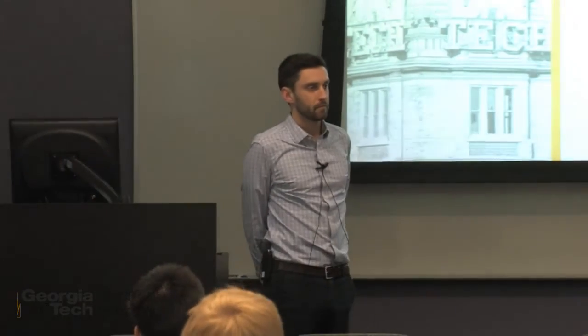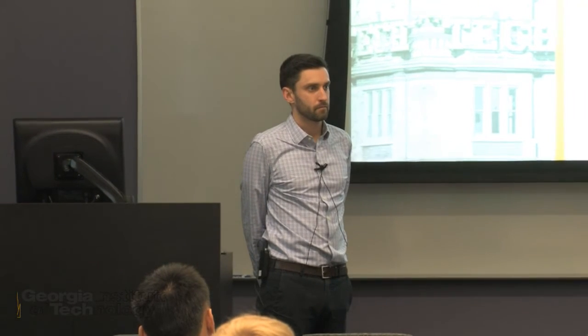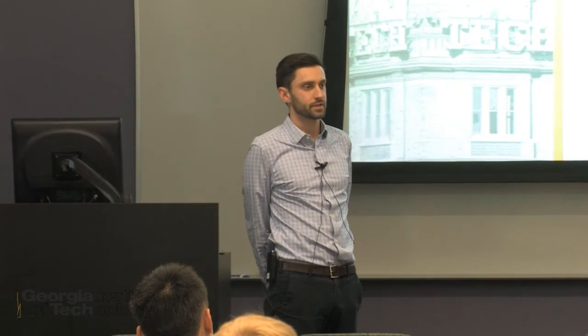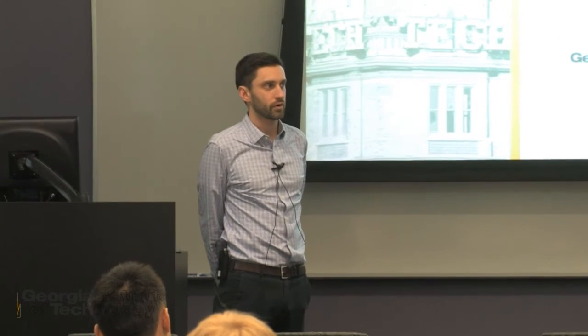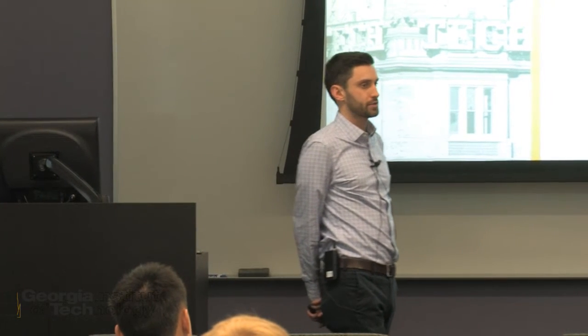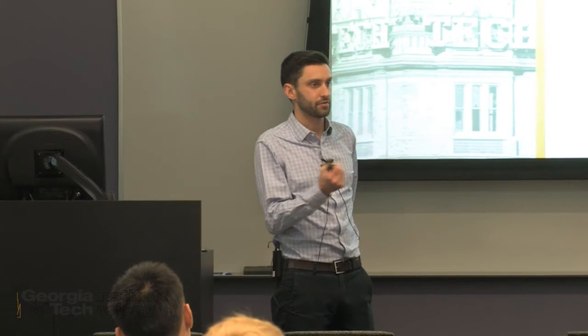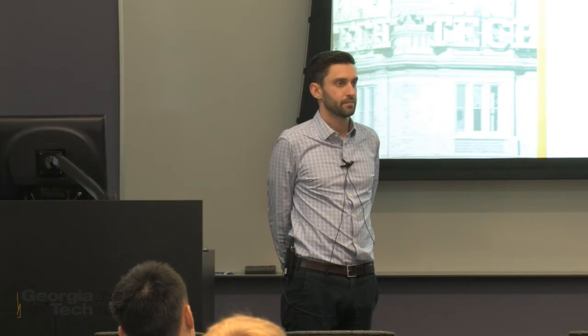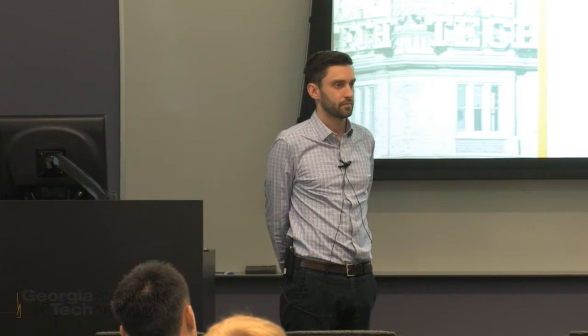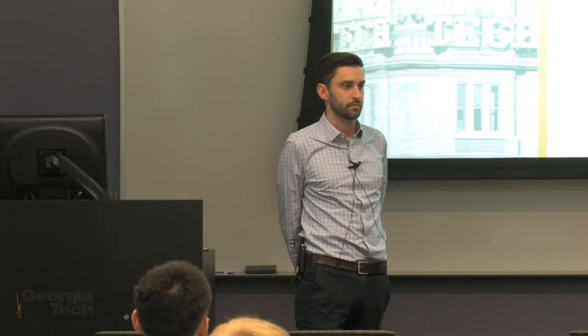Thank you. The copper sulfide lithium system, it should not be reversible. It should have hysteresis. Yeah, large hysteresis. Probably about a 1.5 volt hysteresis. But interestingly, it has a lower hysteresis than other conversion reactions. And it's thought to be due to the fact that copper has a very high diffusivity in the material. Yes, but it's driven by the disproportionation reaction. That's right. That's right. Yeah.